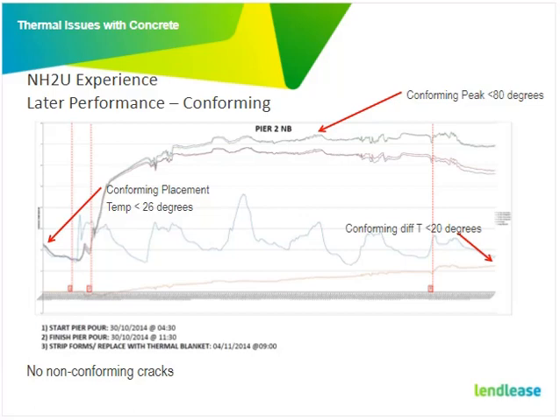The next pour, we got it right. The placement temp was less than 26 degrees, so we managed to get under the 80 degree limit. And again, on the far right you can see where we stripped the form and got the blanket on quickly, and it was just a slight increase. The differential temperature there was only 12 degrees, so it was very well controlled. Those thermal blankets are very effective, and the end result is no non-conforming cracks. So it is effective.